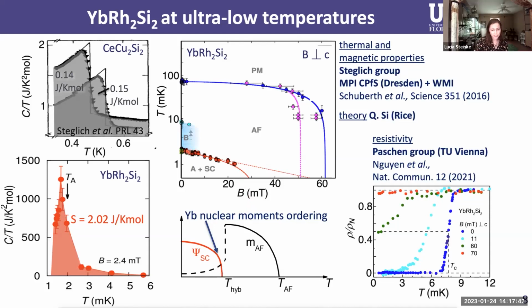And found that, in addition to superconductivity, there is a nuclear ordered phase here that is clearly indicated by the entropy. We could also show that the superconductivity actually does occur at the quantum critical point. So the superconductivity extended all the way to like 60 millitesla. The difficulty here is, because it's a magnetic tuning parameter, the field required to reach the quantum critical point was similar to the critical field of the superconductor. So we are suppressing both at the same time. But this really showed that superconductivity near a quantum critical point is true even for the seeming outlier ytterbium rhodium two silicon two.